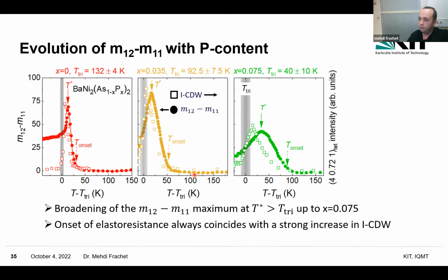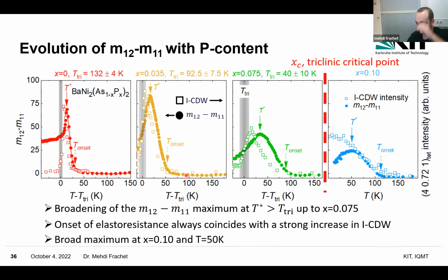So now let's have a look at what happens at 10%. So at 10%, you see that we still have a broad maximum of the elastoresistance at a temperature close to 50 Kelvin. And the onset of the elastoresistance still coincides with a strong enhancement of the intensity of the incommensurate charge wave. Okay.